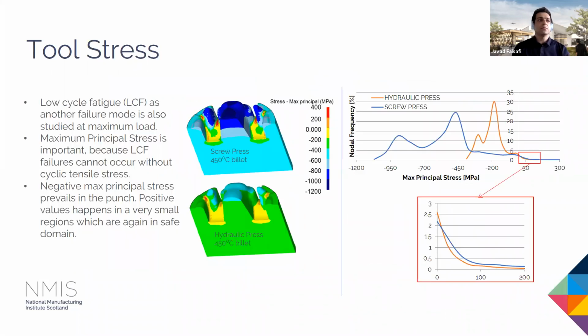And at the end, what we were trying to look at was tool stress and other aspects of tool life. Low cycle fatigue is studied here. You can see the map of the stress across the punch for the screw press and hydraulic press, both at 450. What we are trying to always have is a predominant compressive stress across the parts, across the tool set, because that reduces the chance of any low cycle fatigue happening in the part.